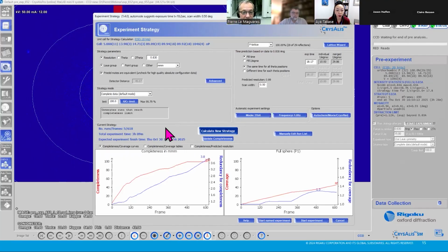So right now, CrysAlisPro tells me that it wants to collect 618 images in 5 different scans, or 5 different crystal orientations. With the exposure time that CrysAlisPro estimated would be good for that crystal, at the top right here, I highlight an exposure time of 15 seconds. The whole thing would take about 3 hours. CrysAlisPro based its calculation of the exposure time on a target I over sigma that we set up in the program. So we want a target I over sigma of at least 15 for the data collection strategy calculation. For the sake of this demo, I will reduce the exposure time to 5 seconds. So now I've got about 50 minutes of data collection time for the purpose of this demo.